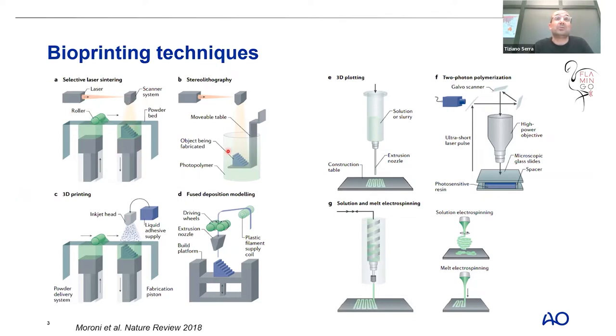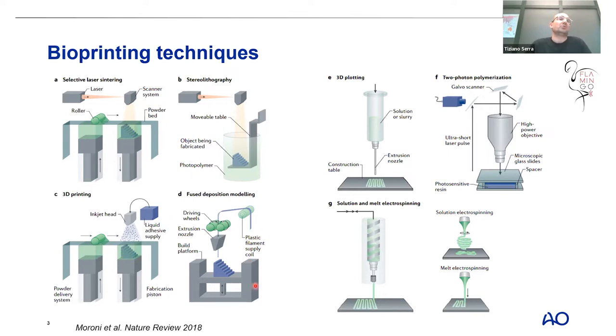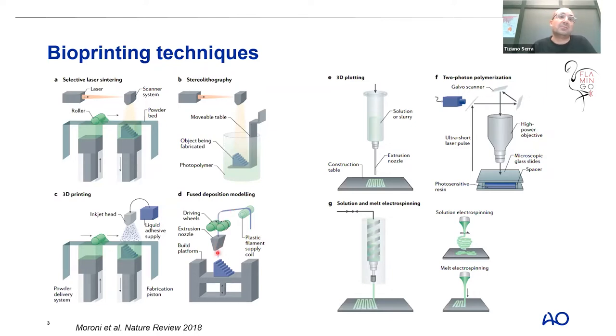Then we have 3D printing based on an inkjet head with liquid adhesive supply, which enables adhesion of thin layers of powder to create specific pore sizes and shapes. Among them also the more classical 3D printing approach: fused deposition modeling (FDM), which uses a plastic filament — mainly a thermoplastic material — extruded through a driving wheel and nozzle, heated at high temperature to melt the filament, and then layering, diffusion, and solidification generates the hierarchically built construct.